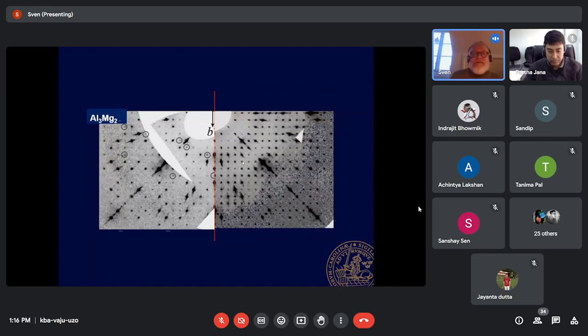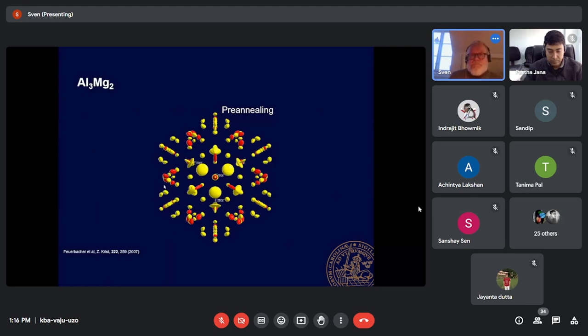Now, what's quite interesting is you can actually solve that rhombohedral structure from the very poor twinned data set to the left. But what you find is that the shapes of the atoms are very strange. You find that there are those which are large spheres, there are those which look like dinner plates, those that look like cigars.